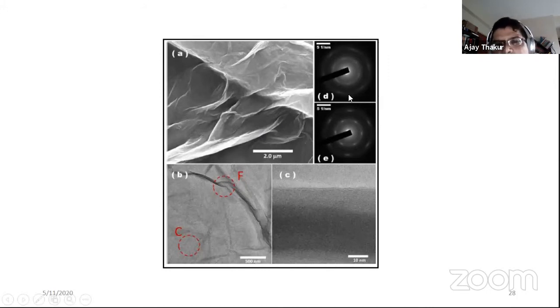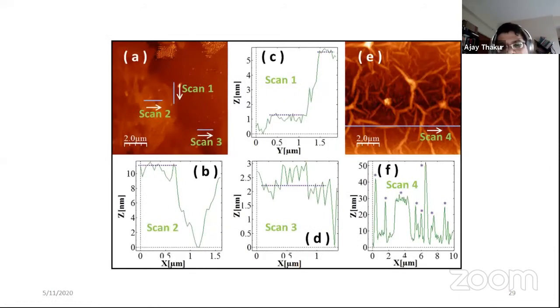On the top right are shown selective area electron diffraction patterns, where we have tried to look at SAED patterns in the fold region as well as in the region where it is flat. What we see is indeed the degree of order in the flat region is higher, because you can see the six-fold symmetric spots, which were not very visible in the top panel. And across this fold, following is the TEM image. AFM was also performed, essentially to look at whether we are getting monolayer graphene oxide.